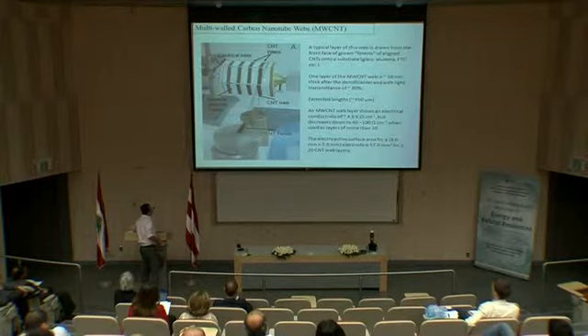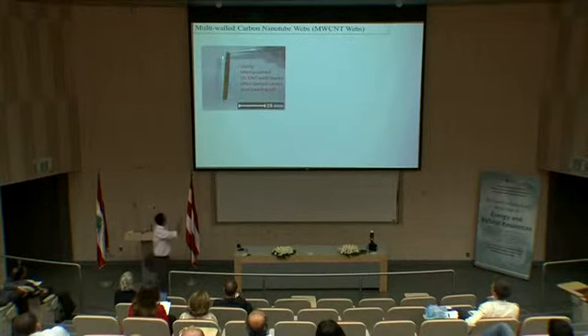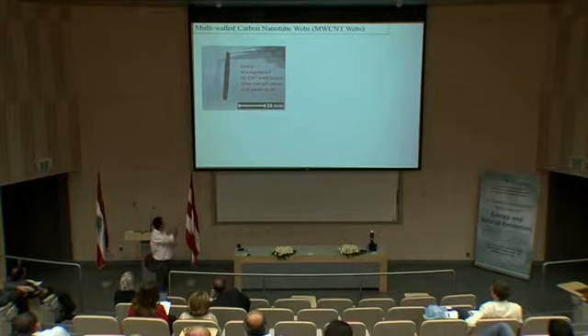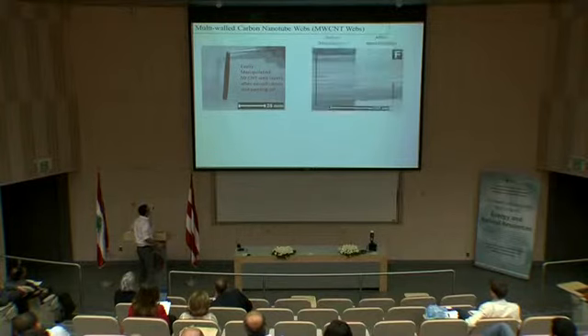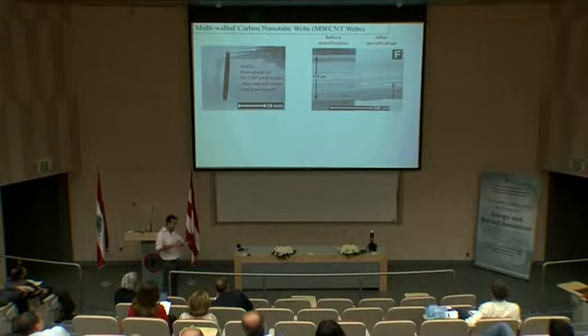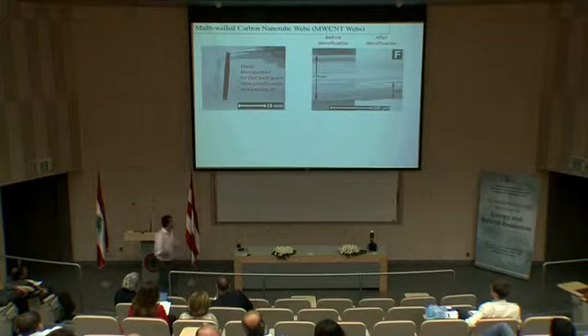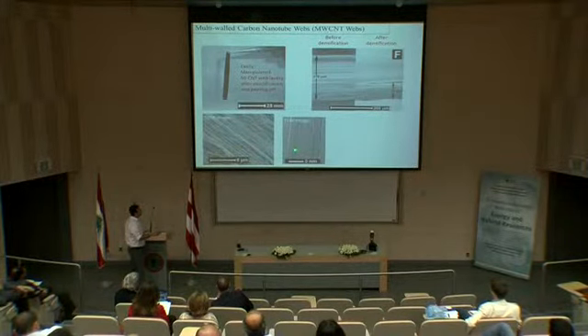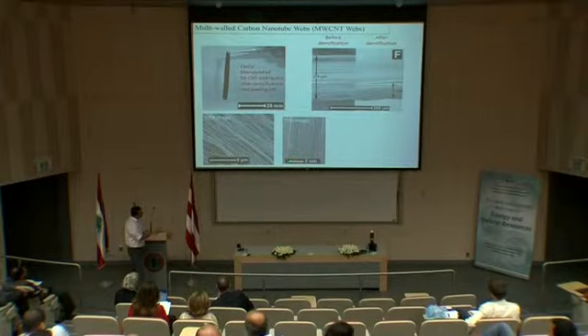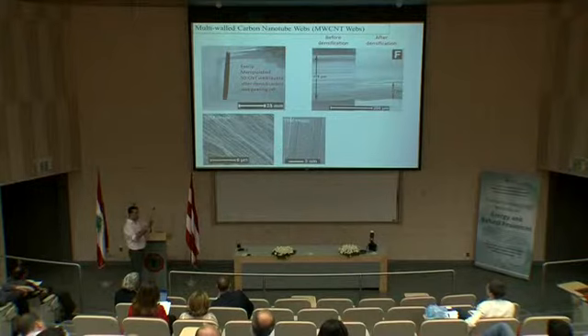Some pictures of these. This is a 50 CNT web layers. These are 50 layers of CNTs that we can manipulate in the lab very easily. This is an SEM picture before and after the densification. The way we stick them to the FTO: we put them on the FTO and drop a drop of acetonitrile or acetone and leave it till it evaporates, it densifies and gets stuck on the FTO. This is another SEM image. This is the TEM image of the multi-wall carbon nanotube. You can see it's around 8 carbon nanotubes within each other.